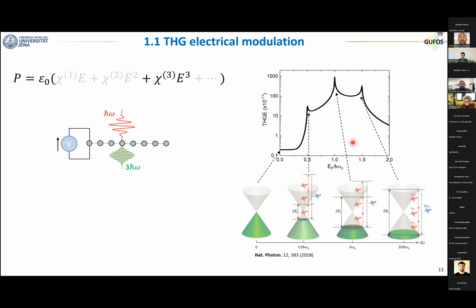And this is why the linear band dispersion of graphene comes into play, and it's very useful, because now you can imagine that your Dirac cone allows for all the possible resonances that we want. And we can start from a condition where the Fermi energy lies exactly at the center of the Dirac cone, that we would call the non-resonant condition. And now clearly by applying a gate voltage and tuning the Fermi energy, we can move across these transitions that would be 1, 2, and 3 photon transitions, as shown in this sketch.